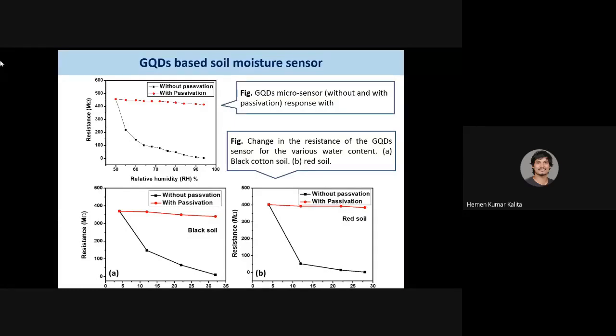So just look at this curve. The resistance is decreasing with the increase in relative humidity. In the case of without passivation, that means where PDMS is not coated on top of the GQD, it responds to the humidity. As we increase the humidity, the resistance starts to decrease, meaning the current starts to increase, in the case of bare GQD. Whereas in this red one, where there is a PDMS coating on top of the GQD, even if we change the humidity, the sensor is not changing its resistance. It is not responding to humidity.